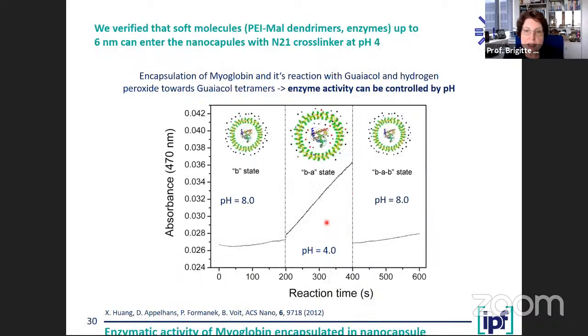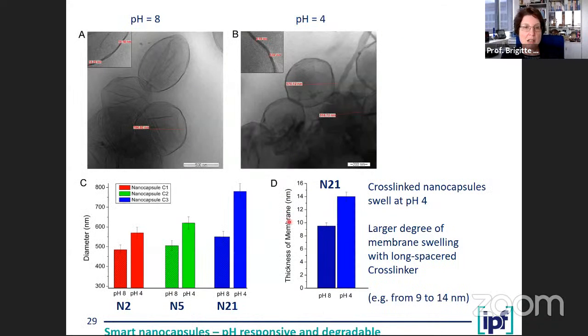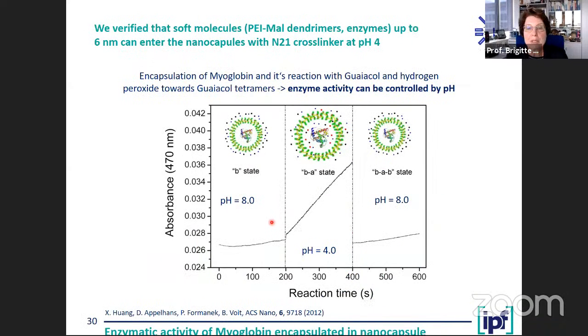And these capsules can be post-loaded. And that's something which is very interesting. The capsules are in the swollen state. They have large holes which allow material which is in the range of a couple nanometers, for example, an enzyme, up to 5-6 nanometers, to move in when they are in the swollen state. And when you then control pH relatively well, it sticks in also. So, then you can use those capsules nicely as reactors, having enzymes inside and having the control by pH between an open and an off state of the material.